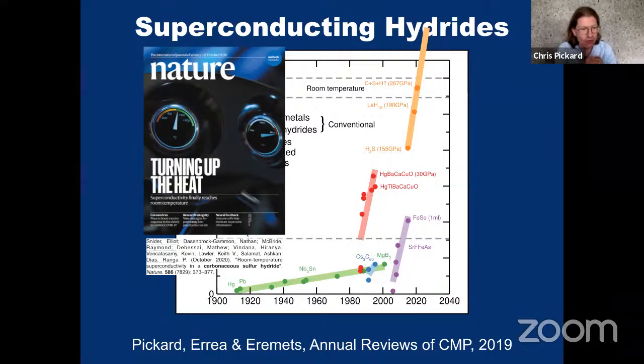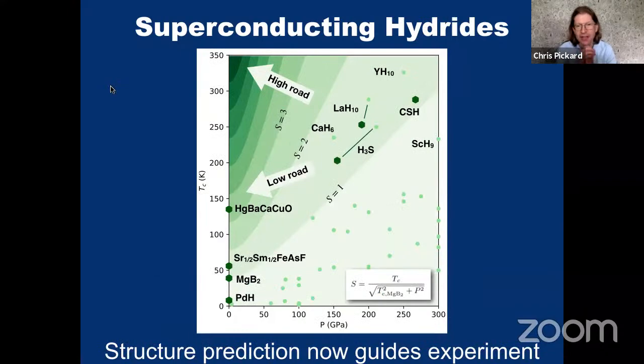And I think this is an important message to get across, especially when you're talking to the public about these, that we're going to have to wait a bit longer for our hoverboards and fusion power. But it is very exciting progress. But I think we need to take stock a little bit of where we've got to, and think about where we'd like to go. So here's a plot adapted from my review article, where I introduced this figure of merit, the S figure of merit, the superconductivity figure of merit, where I weight the TC by the pressure required to achieve it. So I've got TC divided by the square root of the TC of MgB2 squared plus pressure squared. Obviously, it depends on the units you're using here.